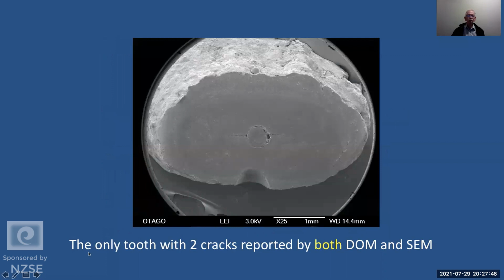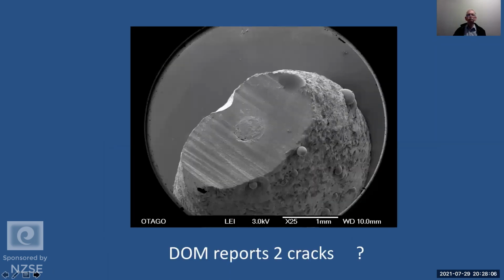And this is the only tooth with 2 cracks that was picked up both with the operating microscope and the SEM. So amazingly, we picked up the crack there, we picked up the crack there, and it was true. But most of the times, we were recording what were in effect untruths.